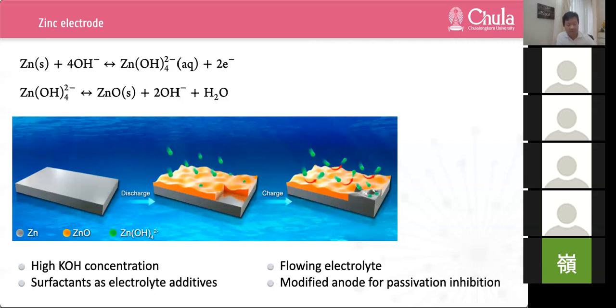The passivation layer is divided into two parts. The inner layer is dense zinc oxide layer, while the outer layer mainly consists of zinc oxide and zinc hydroxide sediments. The mechanism of passivation still needs a deep and unified understanding. The performance of zinc air battery is not only dependent on the zinc electrode, but also strongly depends on the interaction between the electrode and electrolytes of zinc air battery. The composition and concentration of electrolyte can affect the formation process of zinc oxide and further influence the discharge capacity as well as battery rechargeability.